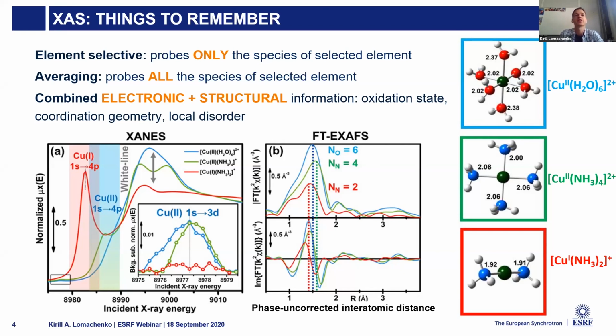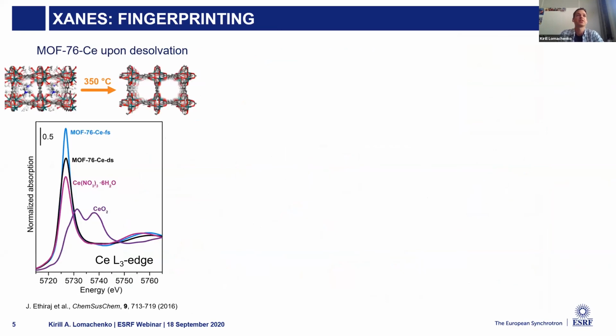Let's start with some examples with increasing degree of complexity. First, a very simple example—we said that XANES can be used as a fingerprinting method. So we synthesized a metal organic framework that contains cerium. Our question is: what is the oxidation state of cerium in this compound, and what happens to this oxidation state when we desolvate the compound, removing the solvent from the pores?